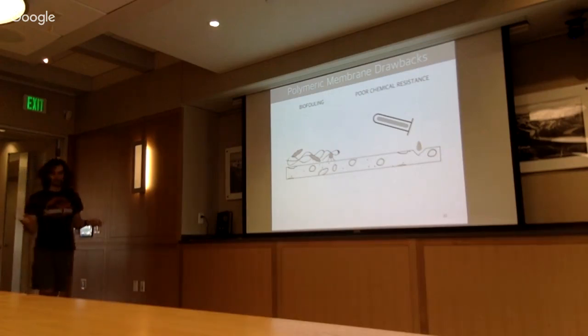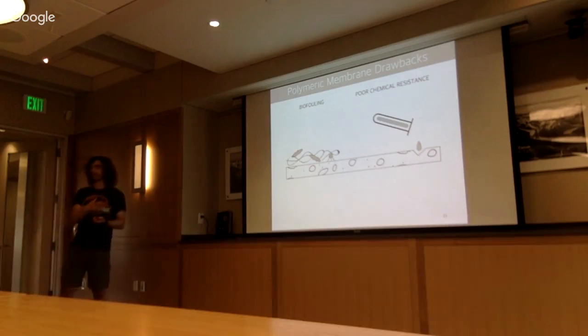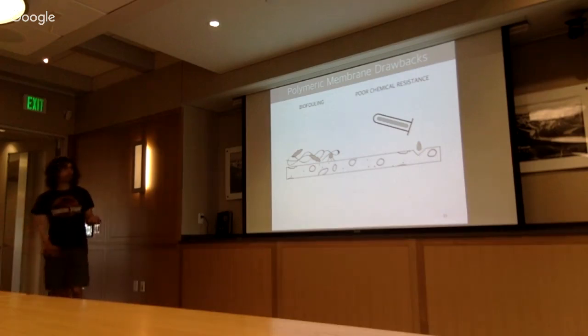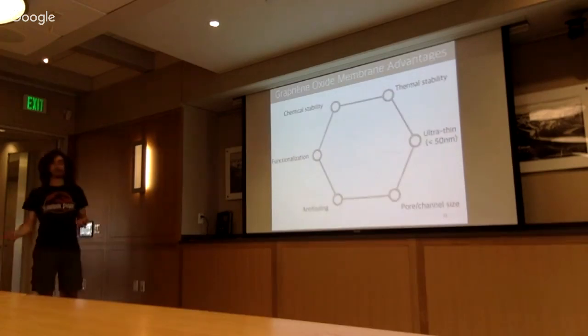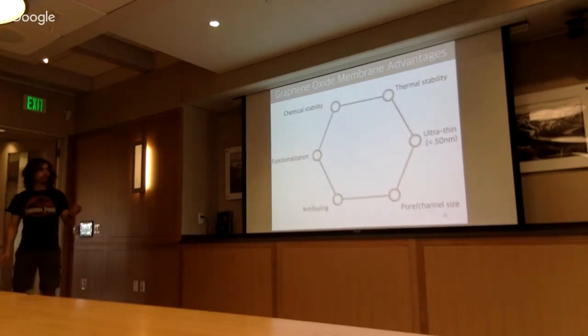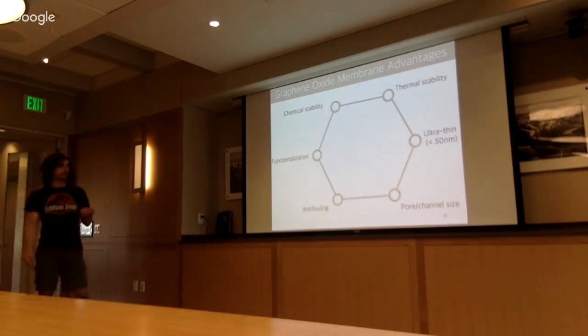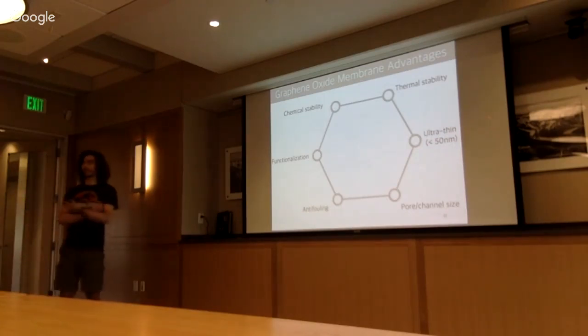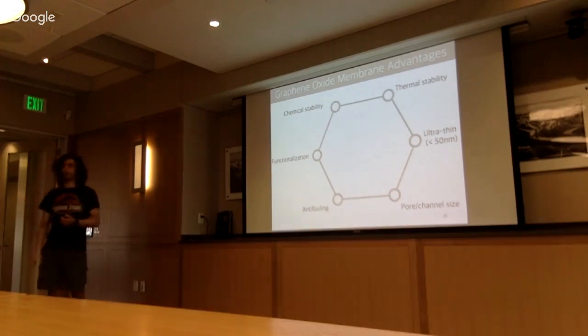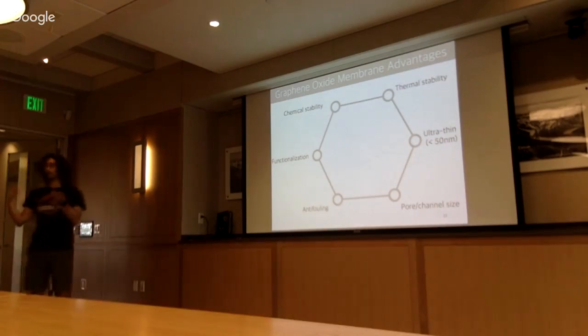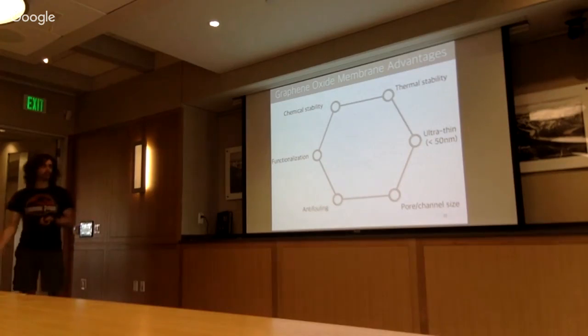So researchers try to avoid this shortcoming by coming up with new materials, and one of these materials is graphene oxide. Why graphene oxide? Because it's chemically stable, it's thermally stable, it's ultra thin. So the thickness is really important because the pressure you need to apply to have the water flowing through this membrane is proportional to the thickness. So if you can make something ultra thin, that means you have to use less pressure and then less energy.